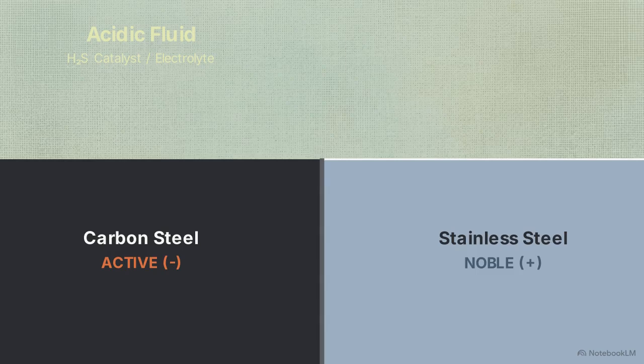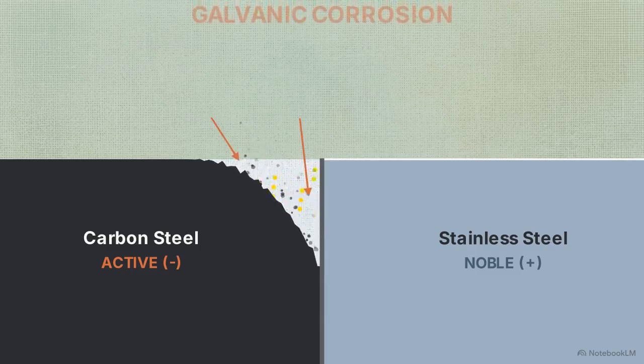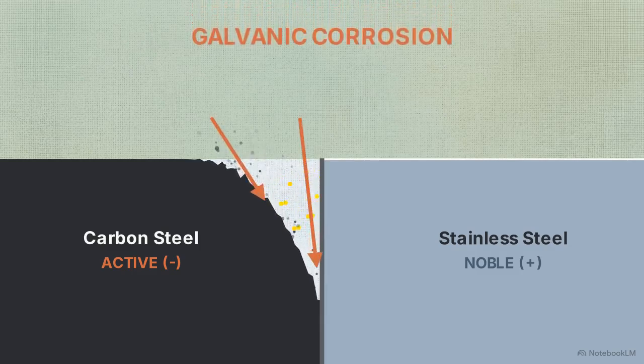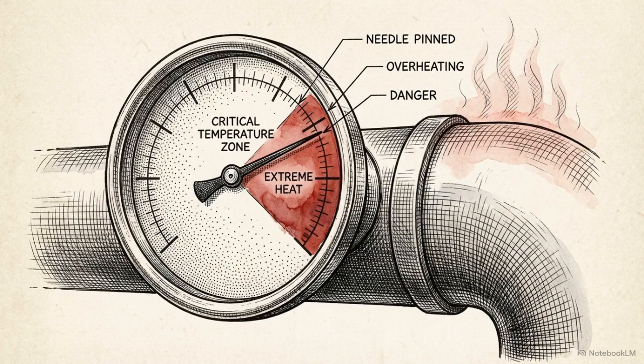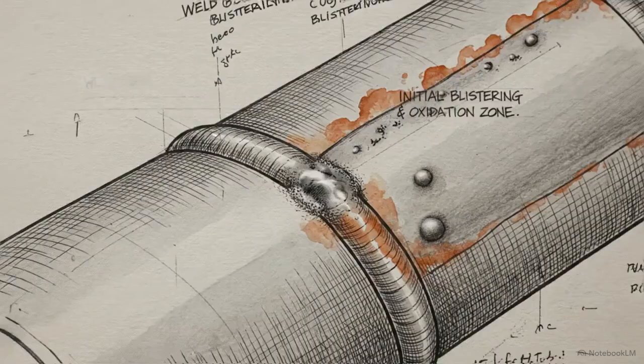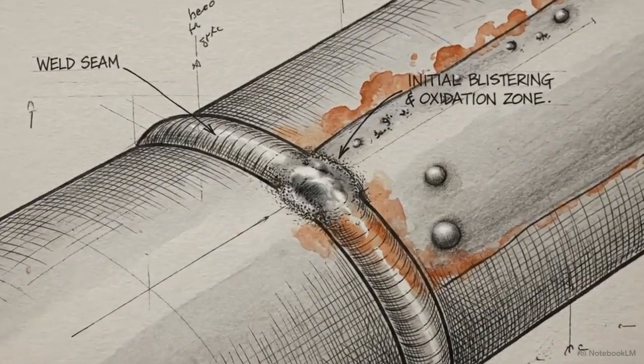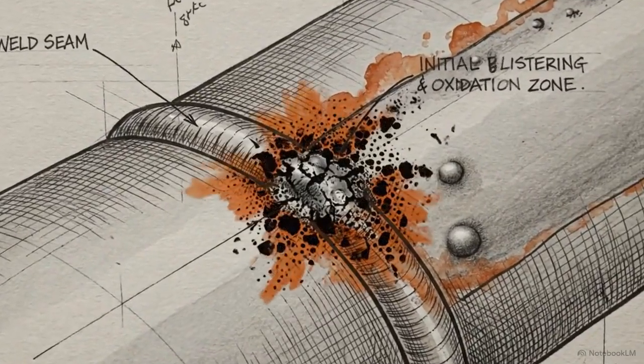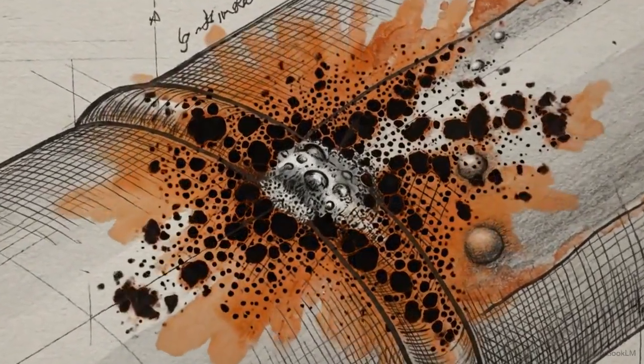Electrons begin flowing rapidly from the active carbon steel directly into the noble stainless steel. As the electrons leave the carbon steel, the metal physically dissolves. This is galvanic corrosion, and it intensely attacks the weaker metal right at the weld seam. Because this system operates at 200 degrees Celsius, the heat acts as a catalyst. For every 10-degree increase, the rate of chemical decay roughly doubles. A welder can execute a structurally flawless pass, but thermodynamic incompatibility will consume the joint from the inside out.